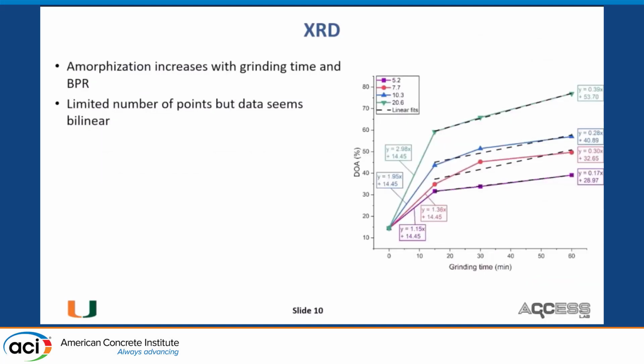So if you look at the degree of amorphization again, and you plot it against the grinding time, there seems to be a pretty bilinear response, limited number of data points, but it kind of seems that this goes up and then it kind of levels off, although it is not exactly horizontal. It does go up a decent bit.